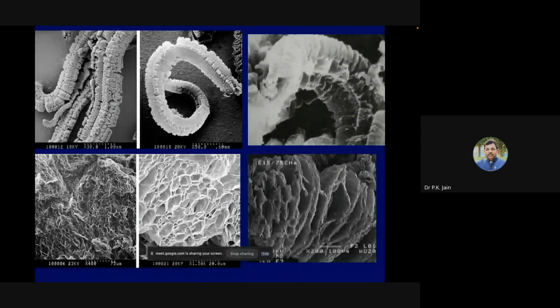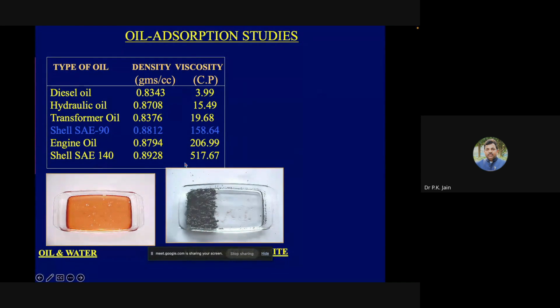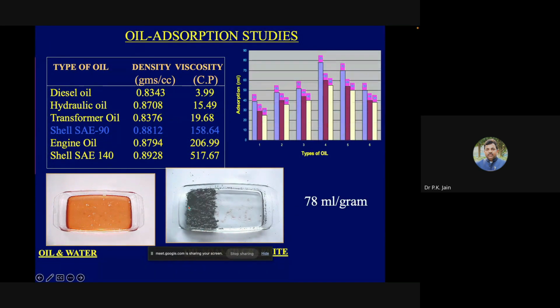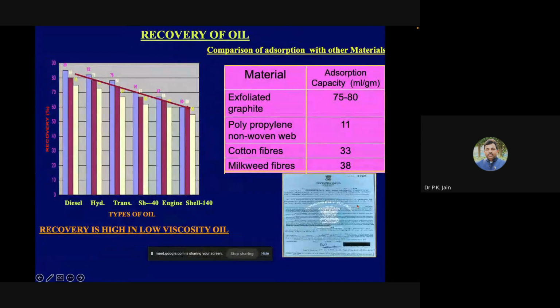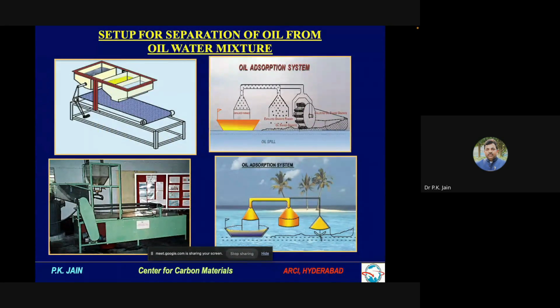Now, if you take this type of highly porous structure, this porous structure will absorb the oil selectively, make it a point. It will absorb only oil from the oil-water mixture. Now, if you see, this is a graphite powder which was put into a simulated condition, and around 78 ml per gram will be absorbed by this. And now you can recover the oil back. Otherwise, earlier people used cotton fiber, milkweed fibers, even sawdust. I remember when we were children, sawdust was used for this.